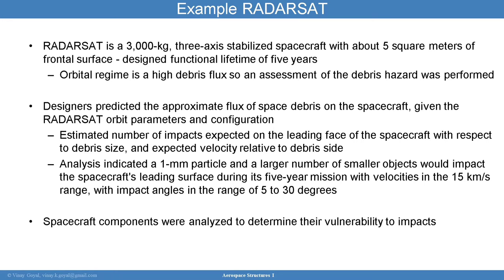And so they estimated the number of impacts that could occur on the leading face of the spacecraft, which is the face that's closest to the debris impact, with respect to debris size and expected velocity relative to the debris. Analysis then indicated a 1 millimeter particle and a large number of smaller objects will impact the spacecraft leading surface during its 5-year mission, with velocities that could be quite large. It looked at 15 kilometers per second with impact angles from 5 to 30 degrees. And so a lot of testing can be done to really understand how the materials behave under the types of impacts you could have.